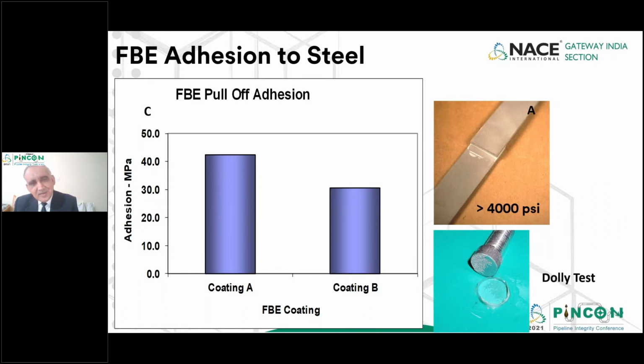bonding. But shear adhesion cannot be done every day. So the panel has to be prepared, bonded, and cured. So it's like one-time qualification testing. But what is more common, which can be done every day, is a pull-off adhesion test, which you see in the green color picture. The aluminum dolly is bonded onto the coated surface by using a structural adhesive. After the adhesive is cured, there is an equipment and the dolly is pulled.